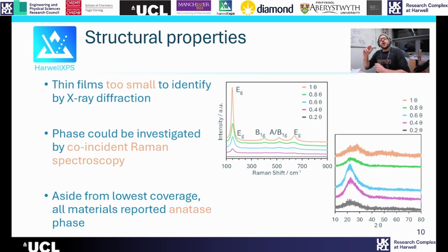Okay, so we know roughly what we expect so far, but we still don't know much about the chemistry. X-ray diffraction was no help, which should be no surprise. The idea is that these films are very thin, so we're not really going to have a large enough crystalline domain to produce enough constructive and destructive interference to give us a diffraction pattern. The Raman was more useful, so 4 of the 5 materials suggested an anatase-like structure, but we still actually have no information on our best catalyst.